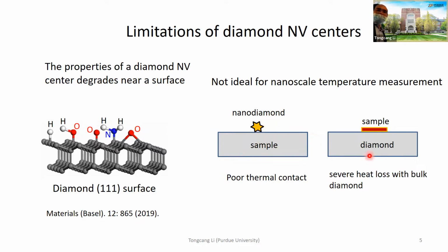But if you use bulk diamond to measure the temperature of a sample, diamond works as a bigger heat reservoir and cannot respond to the temperature change easily. So if you want to avoid this kind of problem, you would like to have spin qubits in a 2D material. Then the 2D material will be very thin, so it has little thermal reservoir, and can also have very good contact to the sample.